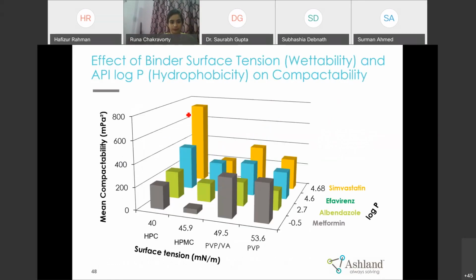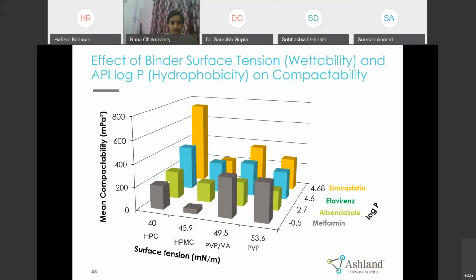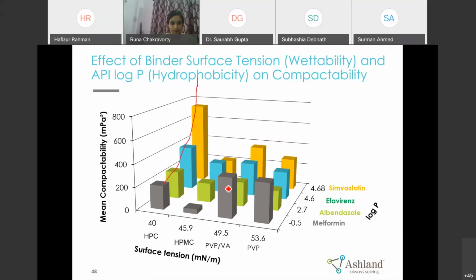So this is our study, a wet granulation case study. We have used different APIs with different log Ps and different binders. With HPC we got lesser hardness in the case of metformin, but as we go from highly soluble API to low soluble API, we get a significant increase in the tablet hardness. So as you can see here, if the API is low soluble, we should use Klucel. If the API is highly soluble, we should use povidone.